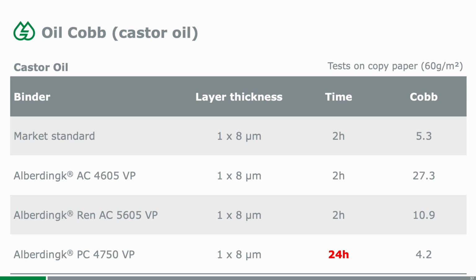If you look at the PC4750, we were testing it for 24 hours, and it still, after 24 hours, outperforms the 3 others. So with 4.2 grams per square meter absorption, that's literally nothing, which again shows that the product is not just hydrophobic, but also lipophobic.